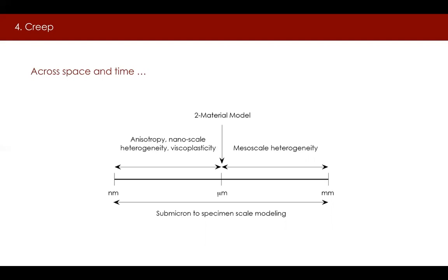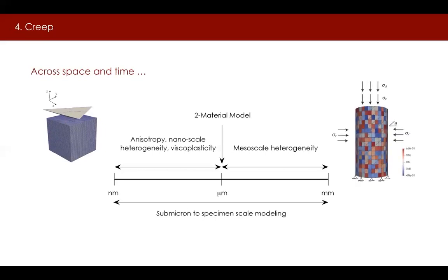Our effort has been inspired by our ability to experimentally probe creep deformation of a shale sample at the nanometer scale through nanoindentation testing, and the creep response at the millimeter scale through triaxial testing. By across time, we know that nanoindentation creep typically lasts no more than 10 minutes.